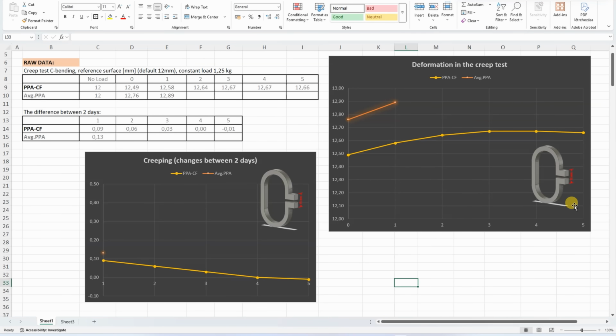On this graph we can see the distance between two reference surfaces, and we can see very small deformation on the Sunlu PPA-CF even compared to the average PPA. But the creeping is the difference between 2 days, and that's what we can see on the second graph. And we can see this is extremely minimal, even some negative values here, because probably this is inaccuracy in the measuring, and slightly better compared to the average PPA.